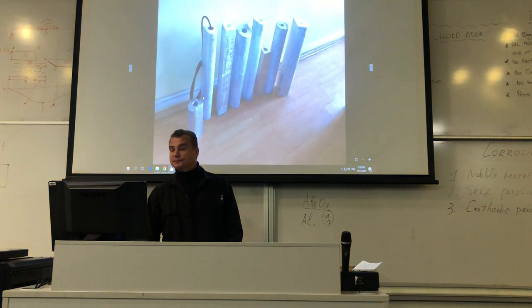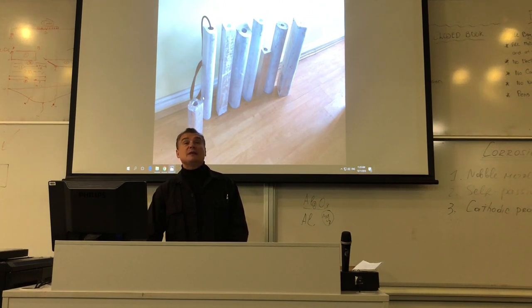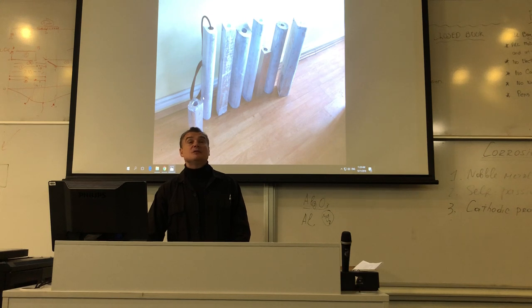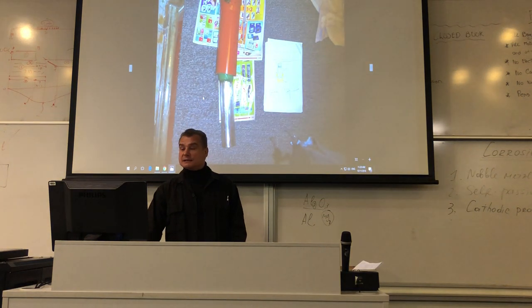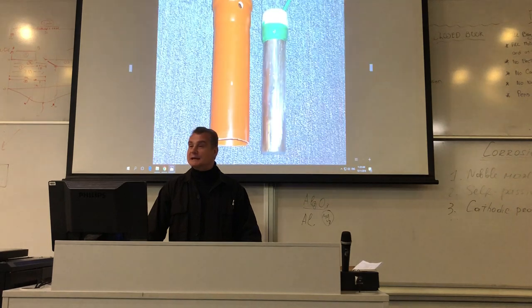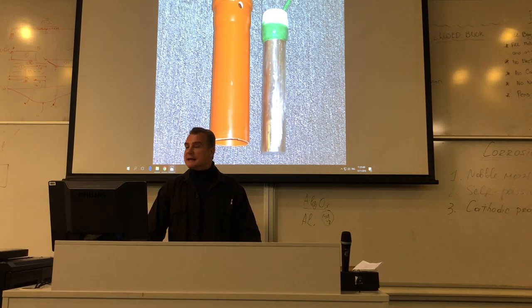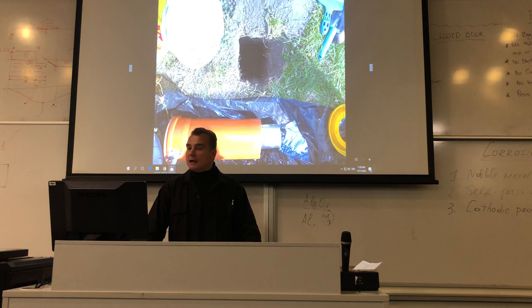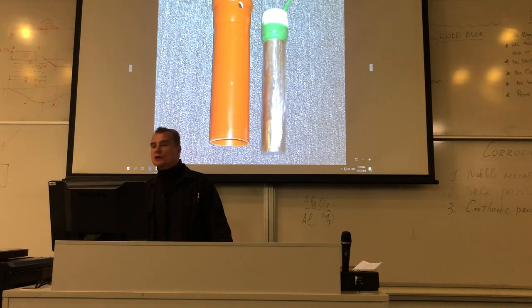Where can we use it? I did a project back in Ukraine. I put a magnesium anode to protect a structure that would not be protected otherwise — it was a fence in a remote area, and without that magnesium the fence would rust much faster. That's a piece of magnesium in a pipe put into a hole in the ground. You could see there's a wire — I would connect that wire to the structure that needs to be protected.